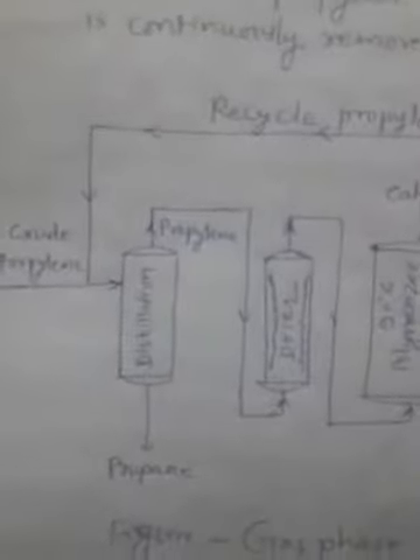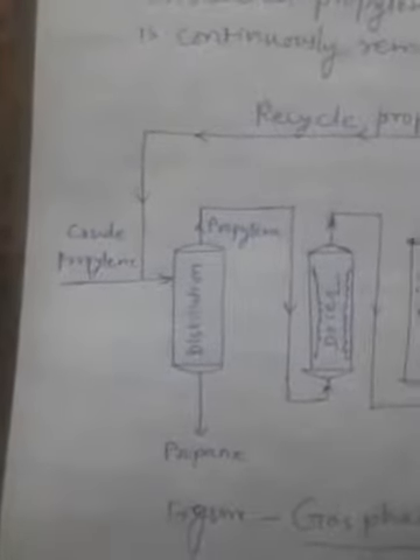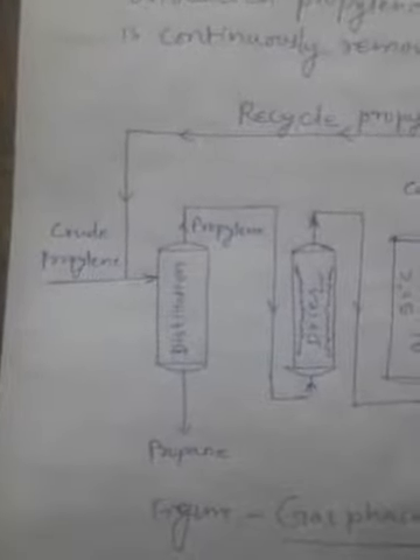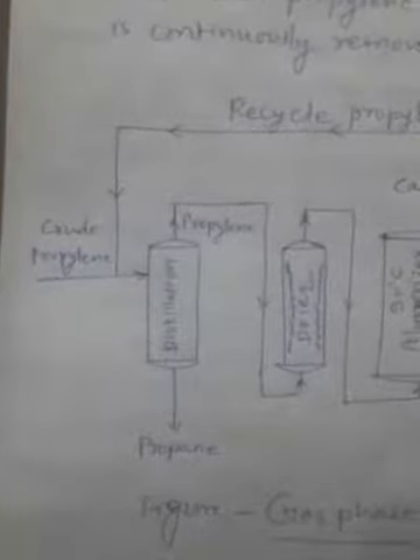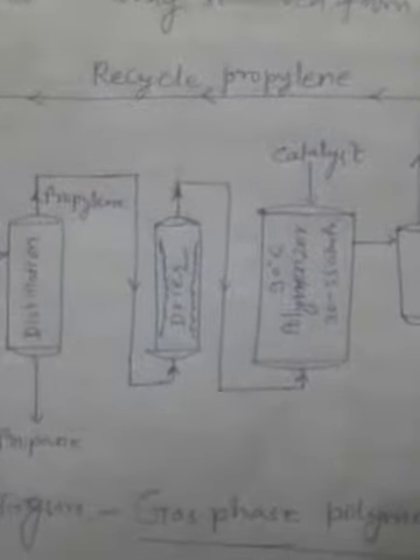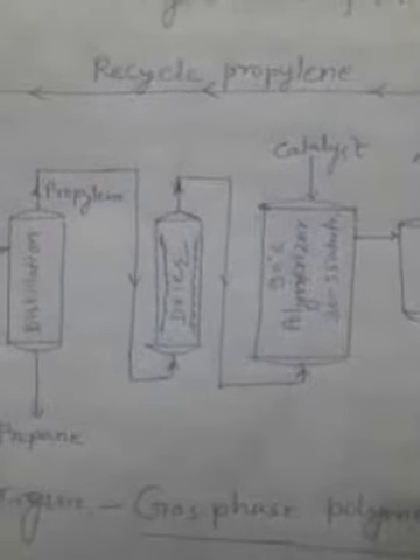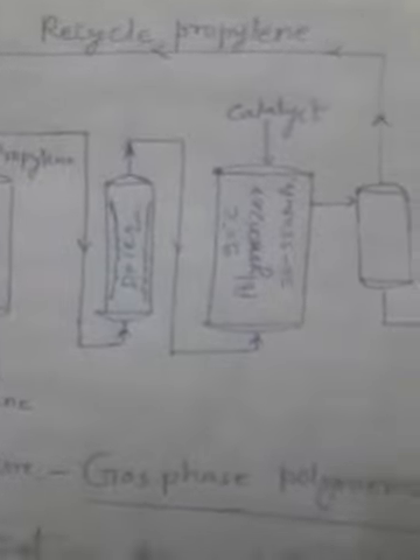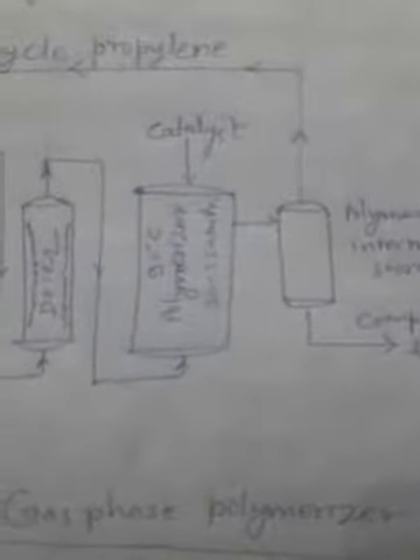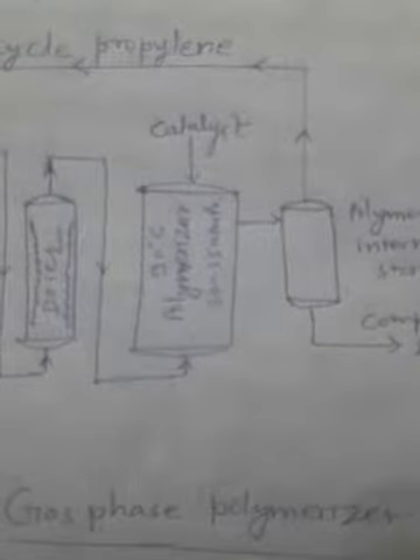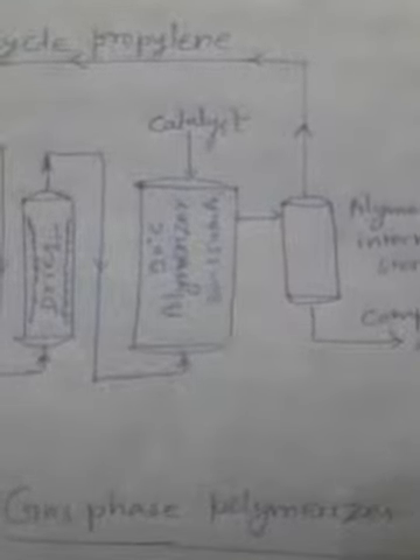In the first step, you can see the crude propylene gas going to distillation, which is the purification and separation of propane gas from propylene, and it is dried by passing through a dryer. So the propylene gas is purified and dried before going to the polymerizer, where it is treated at 90 degrees centigrade and 30 to 35 atm pressure. Propylene gas is fed continuously from the bottom, while the fine particles of catalyst are introduced from the top side.